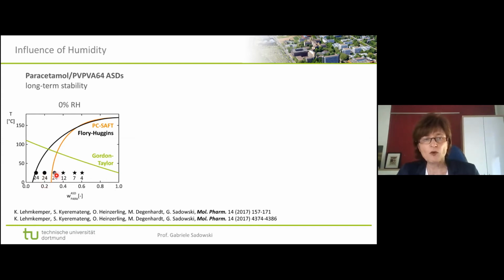The samples right of the solubility line should crystallize at least at infinite time. And what you see is that three of them already crystallized after 4, 7, and 12 months. So you see it really takes quite long, which is nice for the pharmacist. They have a certain time. That's because we are below Tg. So this indeed helps to keep the system at least kinetically stable.